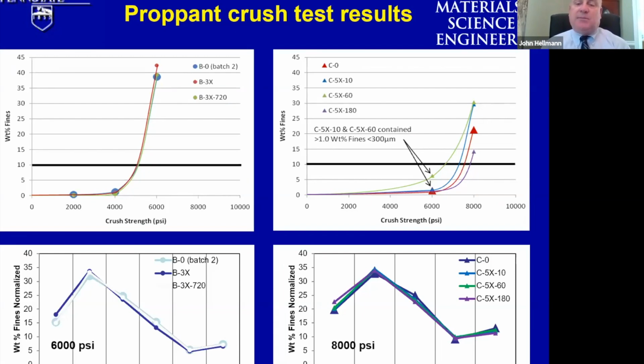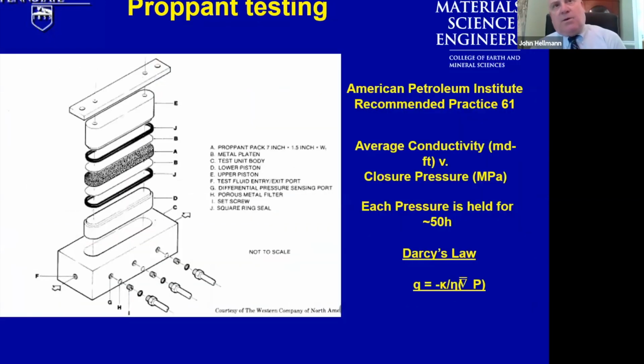And what we were able to demonstrate was that our ion exchange glasses outperformed things like sand and a few other materials that were available for use as proppants in large tonnage quantities. These materials perform well to circa 8,000 psi, which is good news. Those are pressures that are consistent with their use in both the Utica and Marcellus shales and perhaps even out in the Bakken. We then moved on to understanding how these materials behave with respect to permeability.